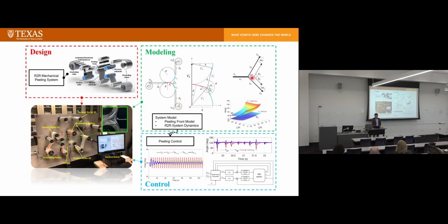We develop a model to model the energy balance. So whenever you generate a crack in the peeling front, we try to balance the energy release rate and the adhesive energy. Because you could have a process disturbance, or you're peeling some devices, and then you're not peeling some certain devices, so the adhesive energy could change. So the process could shift between peeling, not peeling, or peeling with adhesion energy high, adhesion energy low. So the process map could switch.